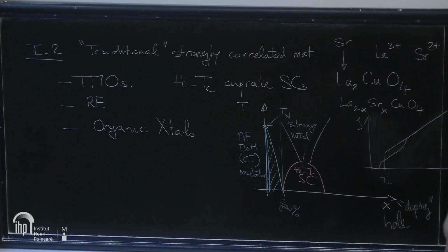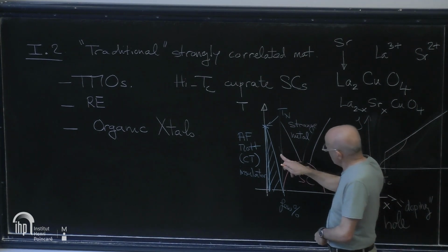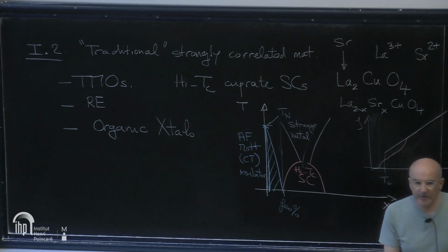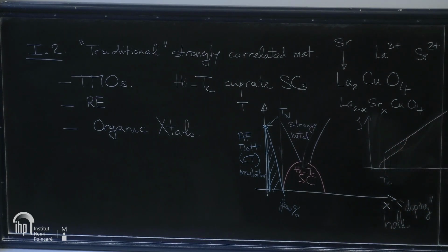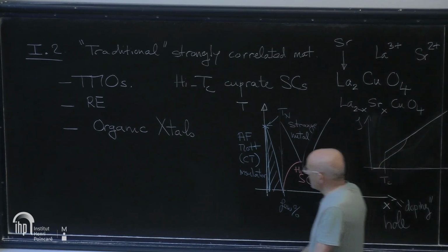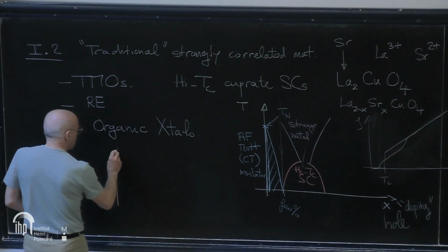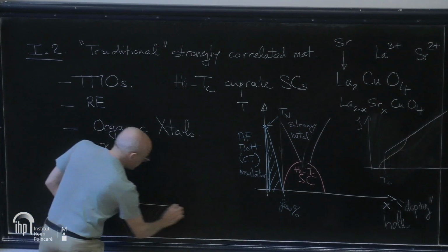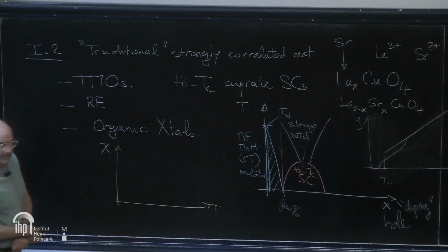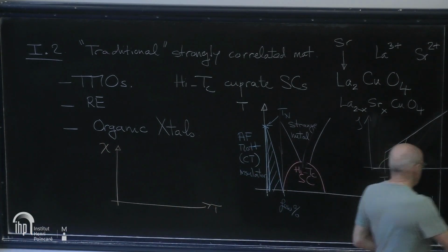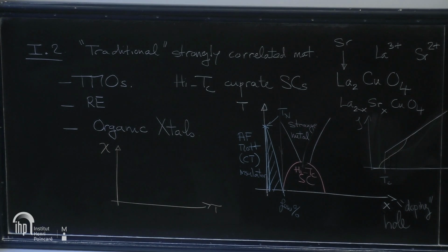So it deviates from linearity. And in fact, if you look at the physics of this metallic regime with other probes, you discover something which is surprising also, which is the following. If you measure the magnetic susceptibility of this metal versus temperature, instead of finding a constant, so another defining property of Fermi gases and Fermi liquids is that the magnetic susceptibility is constant at low temperature, right? This is Pauli susceptibility, right?